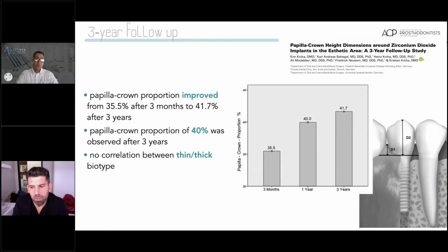This was a follow-up study on the same pool of patients, now looking at the soft tissue behavior around these one-piece zirconia implants. The papilla crown proportions improved throughout the healing process. A papilla crown proportion of 40% was observed after 3 years, which according to Chu is full papilla fill or very good papilla fill. And there was no correlation between thin and thick biotype.